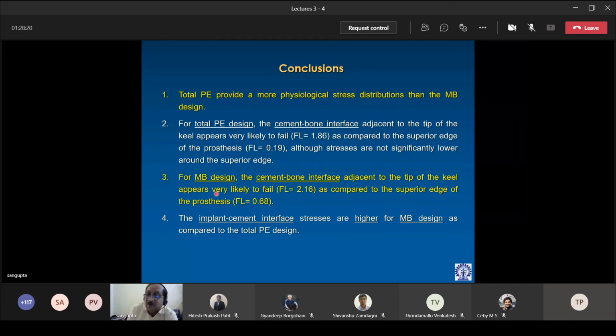For the metal back design, the cement bone interface adjacent to the tip of the keel is more likely to fail because the FL value goes to 2.16 as compared to the superior edge of the prosthesis, which comes out to be 0.68. Okay, so the implant cement interface stresses were higher for the metal back design. Obviously, this can be the only answer, because if you compare the values, it is evident that the metal back design would produce higher implant cement interface stresses. So this is the evaluation of the cement bone interface, but in the case of the implant cement interface, you have higher values for the metal back design as compared to the total polyethylene design.